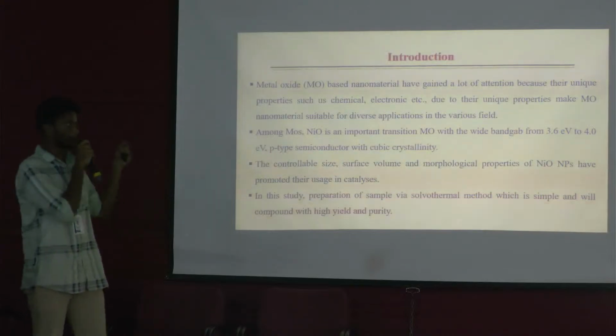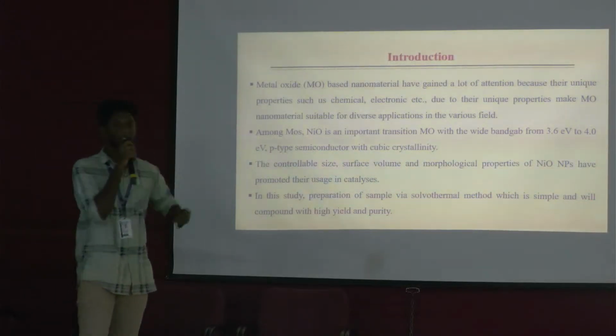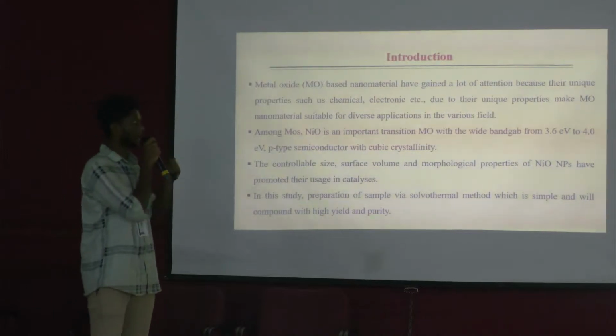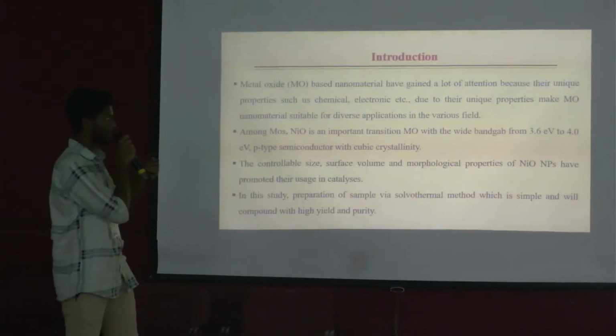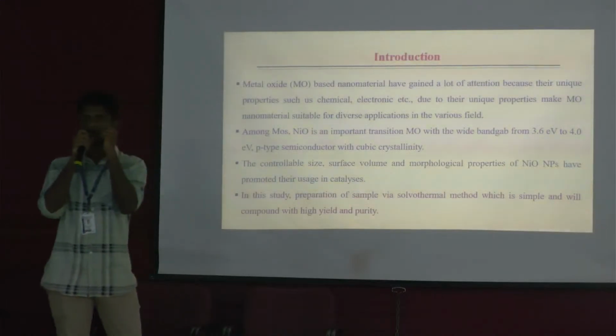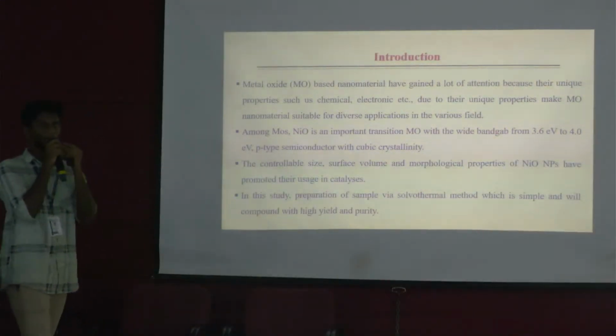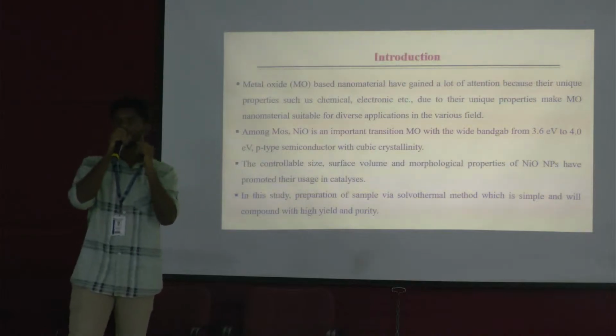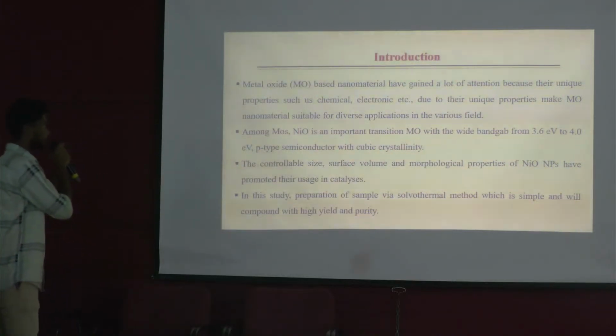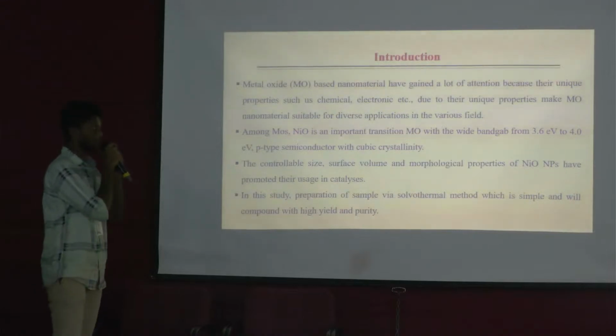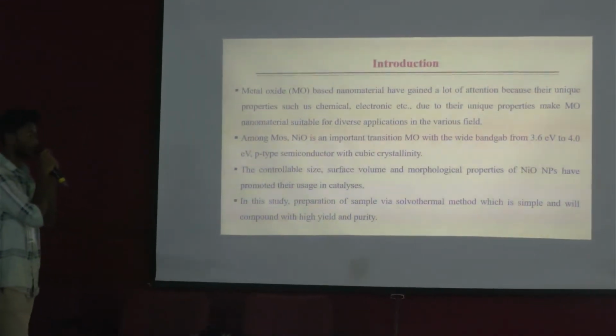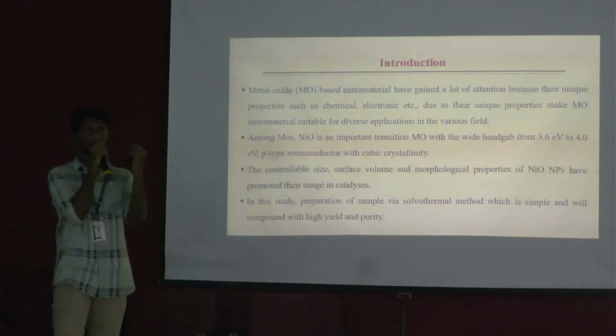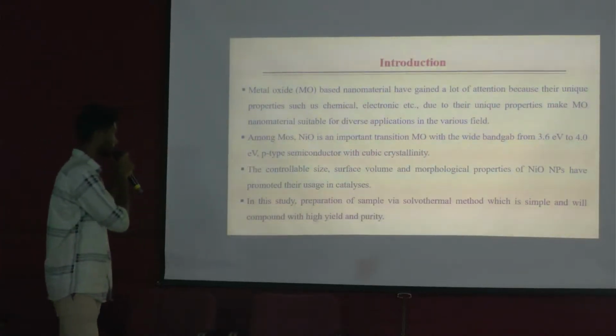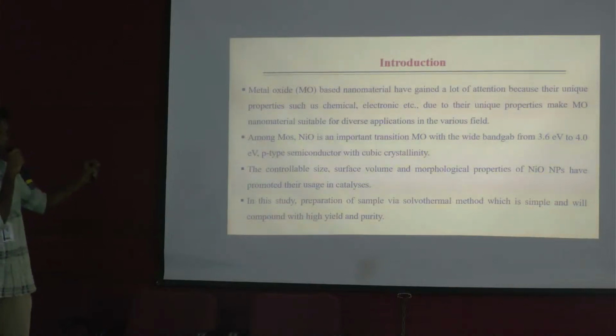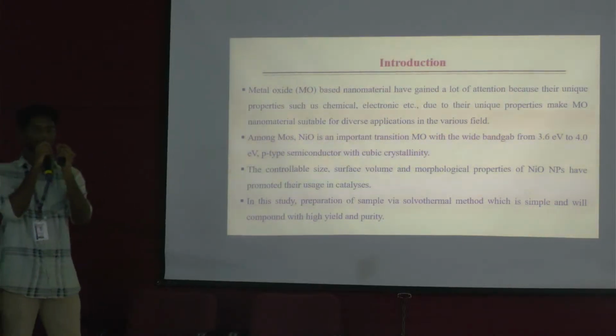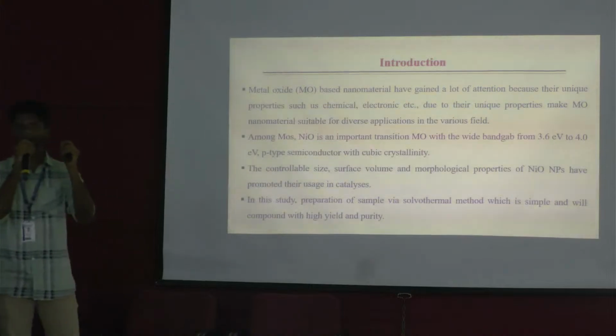Among metal oxides, nickel oxide is an important transition metal oxide with a wide band gap from 3.6 electron volt to 4 electron volt. We all know the band gap is the energy gap between the conduction and valence band. The controllable size, surface area and morphological properties of nickel oxide nanoparticles have promoted their usage as catalysts. In this study, the sample is prepared via the solvothermal method, which is simple and gives compounds with high yield and purity.